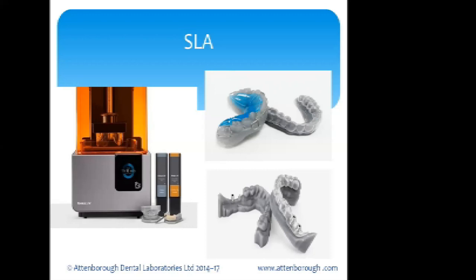And I think you need to be aware of that when you're talking with your labs, as more and more labs bring in 3D printing, that we make sure that they're using validated workflows, because the photo initiator in these materials is carcinogenic. So we really don't want to be putting any of that in the oral cavity without being 100% sure that it's fully cured.